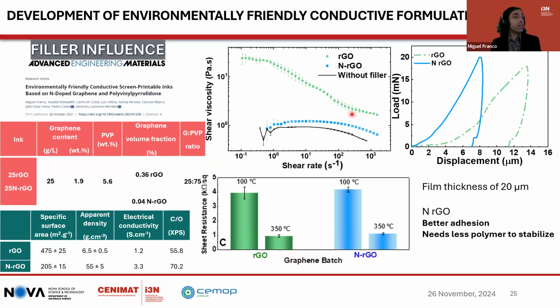So in this case, the ink design depends on the intrinsic properties of the filler, and due to these properties, we need to study and design the amount of binder needed to stabilize the ink and give it the desirable characteristics. For example, graphene has a very low density and a very high specific surface area, so it's very hard to make inks with a higher graphene content in terms of weight percentage. But if you were using oxides or other kinds of fillers, you can see these values are quite higher. I don't know if I can answer the question.